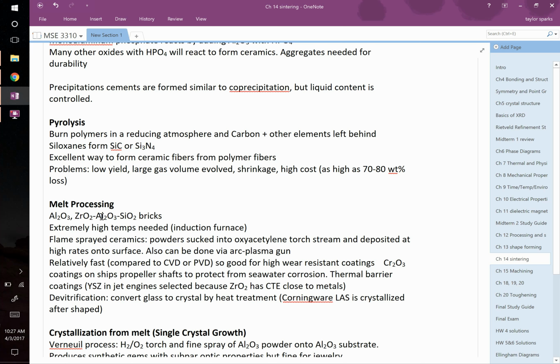Why is this good for making fibers? Garrett? Well, I was going to say fibers are typically very strong. They don't have very many flaws. Oh, sure, we know why we want fibers. Because their volume is small, they have low statistical odds of having a flaw in them. Is it easy to make polymer fibers? Pretty darn easy. Compared to ceramics, definitely way easier. So what if you took a bunch of these long polymer fibers, laid them in your furnace, and heated them? Now it's going to shrink, obviously, as you burn stuff off, but you're going to be left with a ceramic fiber.